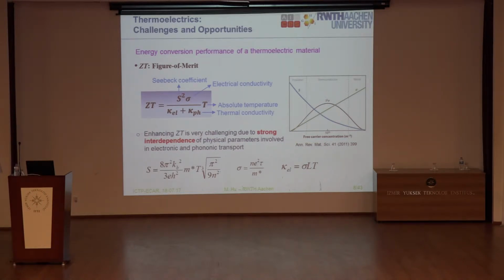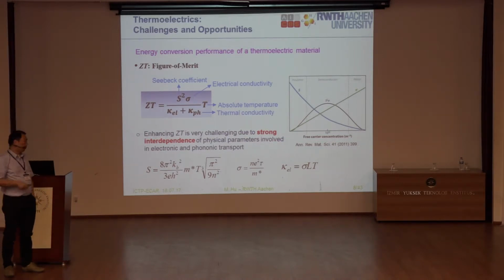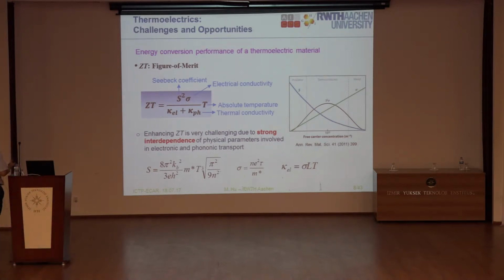So actually, so far there is no 100% accurate method that can predict this ZT coefficient very accurately from the fundamental science point of view. So far, most of the studies focus on the S squared sigma, just taking a look at the power factor, and use some traditional model to treat the phonon transport and electron transport. But for example, my expertise is focused on micro-nanoscale heat transfer, so we can accurately calculate the phonon transport part, but the effect on the power factor is sometimes a weakness. Anyway, if you want to enhance the ZT coefficient, you have to treat this coherently, not just some individual term.